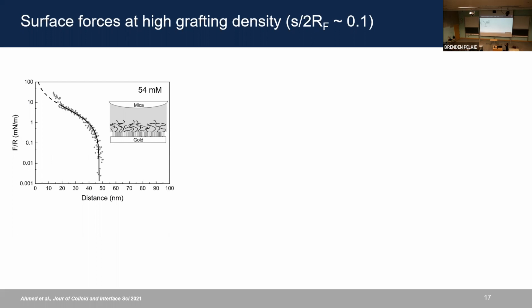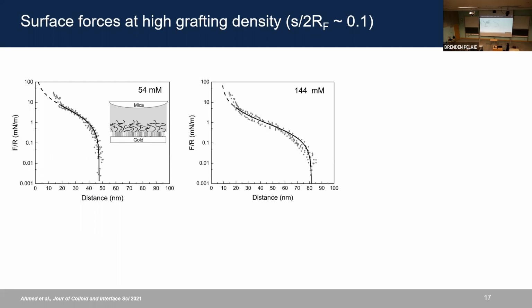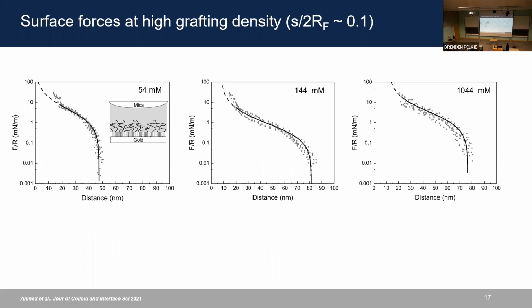So with decreasing distance, the interaction forces increase, and the onset of repulsion is pushed back further, to 80 nanometers, and it remains about the same for even higher ionic strength, or salt concentration, of the surrounding solution.